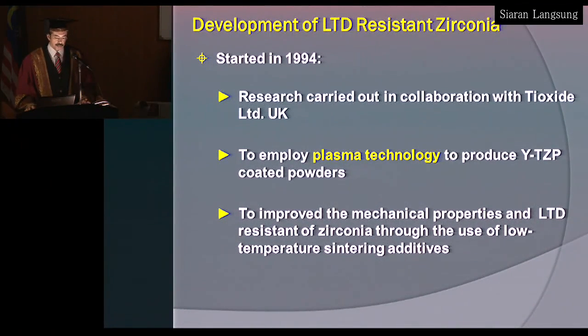So basically, the development of LTD-resistant zirconia in the case of my work started in 1994. This is research done with Tioxide UK. Basically, what we did was to use the plasma technology used to make titanium dioxide in order to coat yttrium onto zirconia particles. The objective is to improve the mechanical properties and to reduce or suppress LTD by the use of sintering additives.